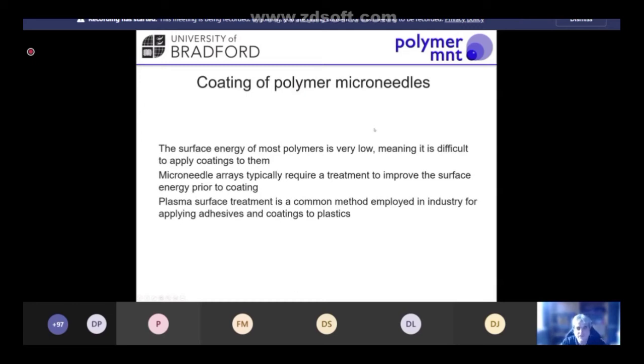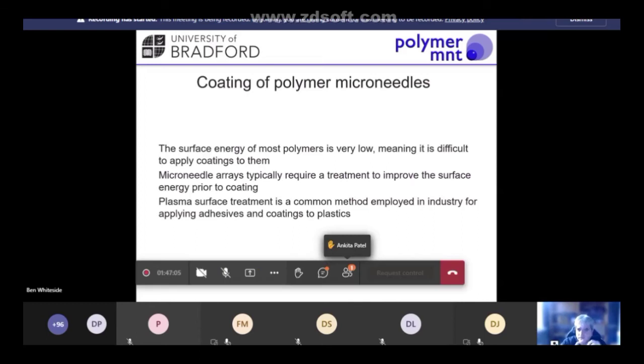Now, one of the challenges we have with coating any microneedle array is the fact that the surface energy of the polymers is very low. So basically, things don't want to stick to them, so it's difficult to get coatings to attach. So what we've worked on over many years now is treatments to improve the surface energy prior to coating. And we generally just use an industry standard for many polymer components, which is plasma surface treatment. It's a common method employed in industry for attaching labels or adhesives to plastics.